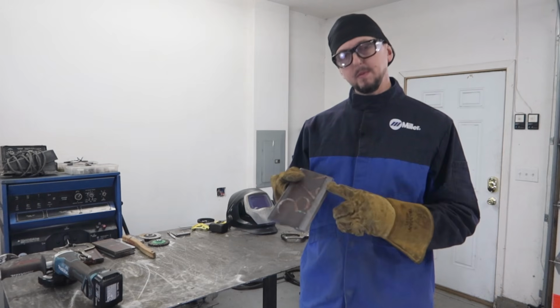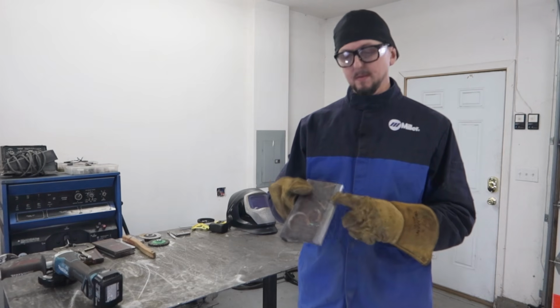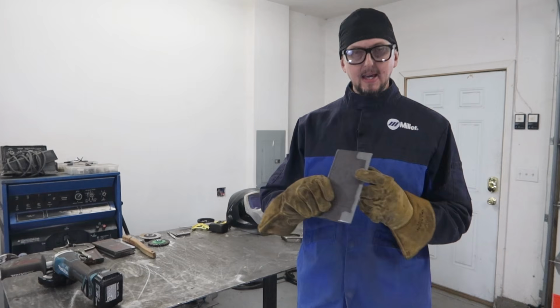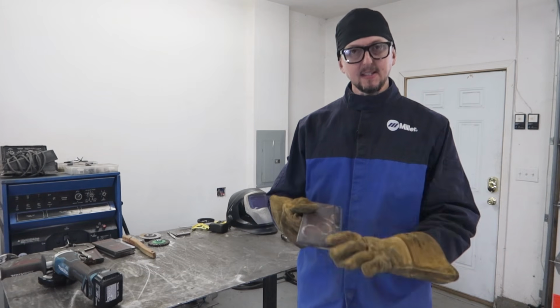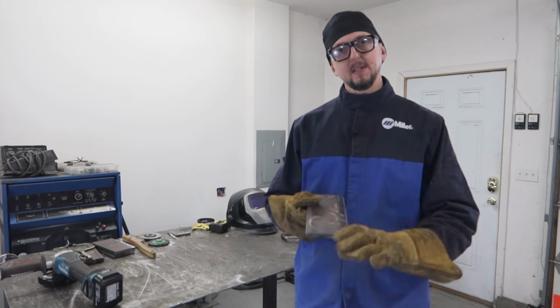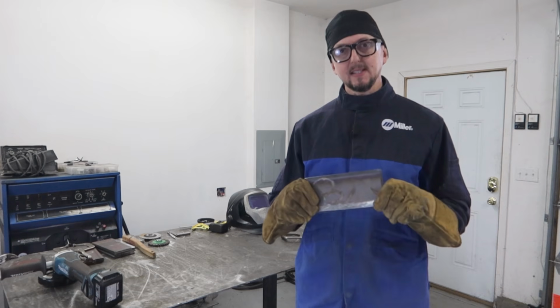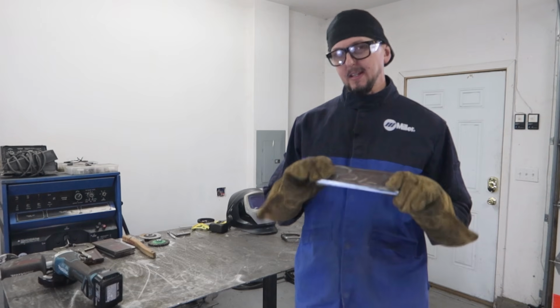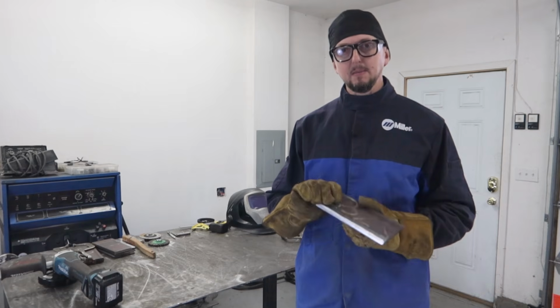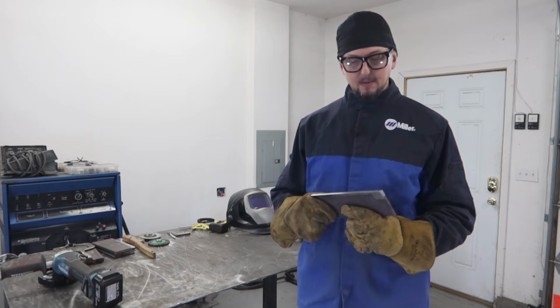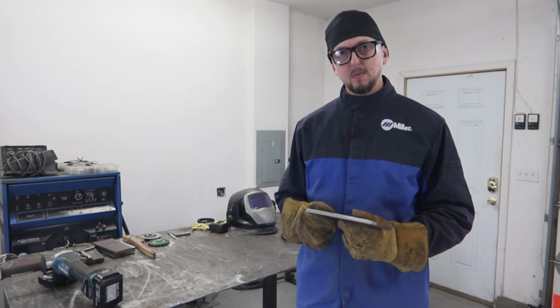Okay, so now we've removed the mill scale from the top side of the weld, the bevel itself, and the back side. So we've got it nice and clean because that mill scale will actually act as an insulator, and it'll just keep a little bit of the current from being able to go through. So we want to remove all that before we start welding.